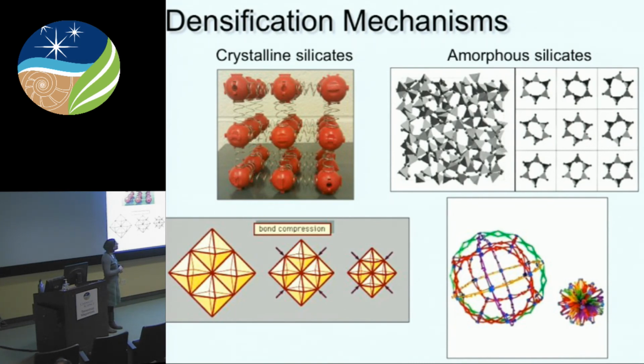However, because of the lack of long-range order in amorphous silicates, you have additional degrees of freedom. The rigid polyhedra can rotate relative to one another to reduce volume, and this is a very low energy way of reducing volume that doesn't actually compress the silica tetrahedra. The way I think about this a lot, we've all seen these toys at science museums, a plastic ball that you can expand and contract just by the relative rotation of the plastic parts. So this is the mechanism that we are proposing is active in amorphous silicates that can account for the wide range of anomalous behavior that we see. And because of this, crystalline equations of state won't predict the high pressure properties for silicate liquids.